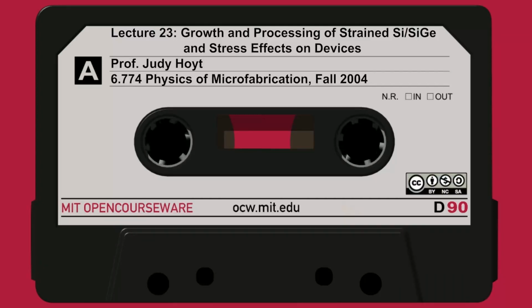We talked a little bit about strain, and here on slide 27, I'm showing a little bit of an idea what that means. This ball and stick diagram on the lower right was our pictorial picture in our heads. When the epi layer is thin, we said the silicon germanium, if it's thin enough, will compress in X and Y. It will match the lattice parameter of the thick substrate. That's only when it's thin enough and it's energetically favorable to bend the bonds. In that case, we say it's fully strained. If you build up more and more layers, you build up more and more stress. At some point, it becomes energetically favorable to break bonds.